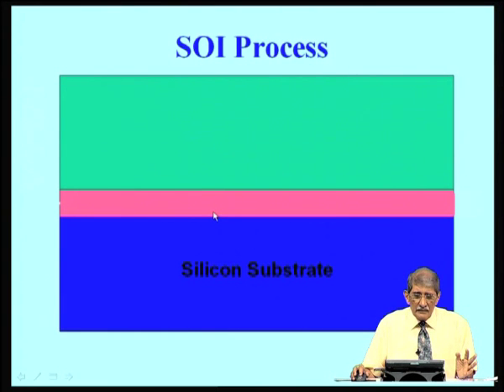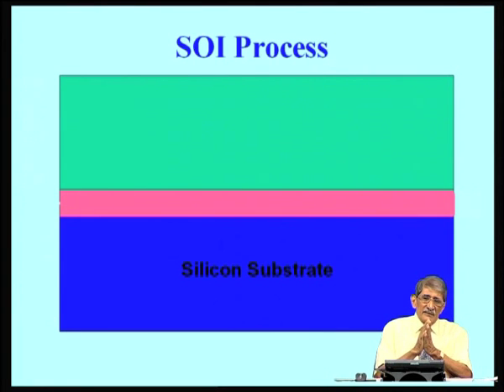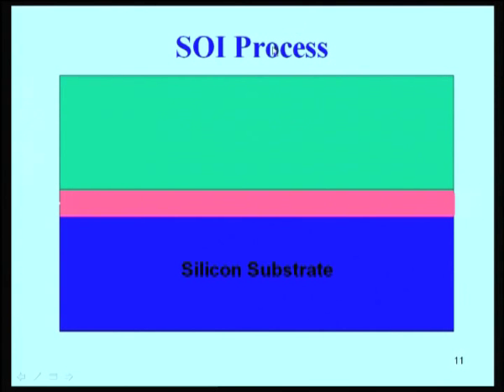The technique is, initially when you bring them together, the initial bonding takes place because of some OH which is present on the surface. You have to give some chemical treatment, so that the surface becomes hydrophilic, that means water loving. Hydrophobic is water hating. So, we make it hydrophilic by some chemical treatment. There will be OH molecules, and when you bring them together, the initial pre-bonding will be between silicon, OH, silicon. Then you take it to high temperature, so that the hydrogen comes out from the OH and you have silicon, oxygen, silicon, that is SiO2 bond. You will have the bonding through the SiO2 itself. That is, the two wafers are bonded.